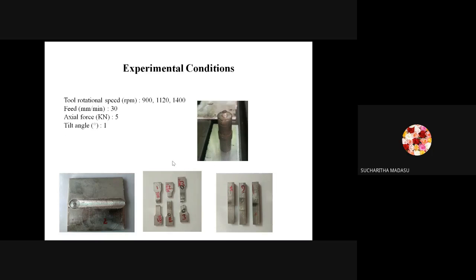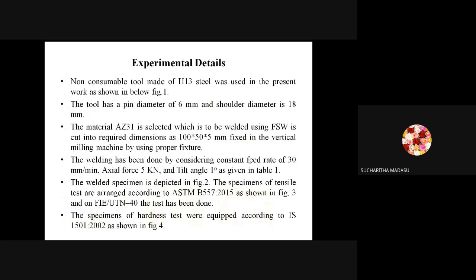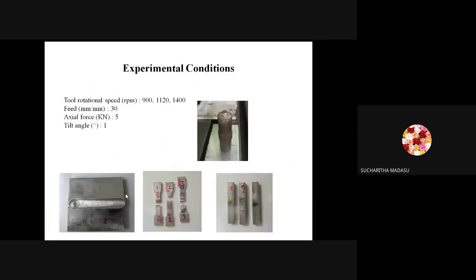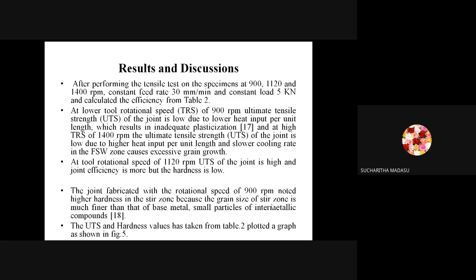And here the welding has been done by considering the details already given. Actually, I have done this work on a vertical milling machine. So this is the tool diagram, and this is the diagram after welding. Here I have done the tensile test as well as hardness and microstructure. After performing the tensile test on specimens at 900, 1120 and 1400 RPM, constant feed rate 30 mm per minute and constant load 5 kilonewtons, I already have given that diagram.